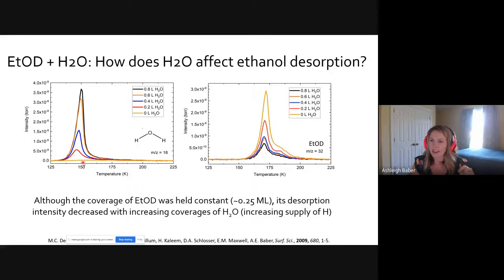The weird thing, though, was that we're aiming for consistent amounts of deuterated ethanol on the surface. So we should see the same amount of deuterated ethanol coming off of the surface as we add more and more water, and that's not what we saw. We actually saw less deuterated ethanol coming off of the surface as we added more water. So where is that deuterated ethanol going? Well, it's not really going anywhere.